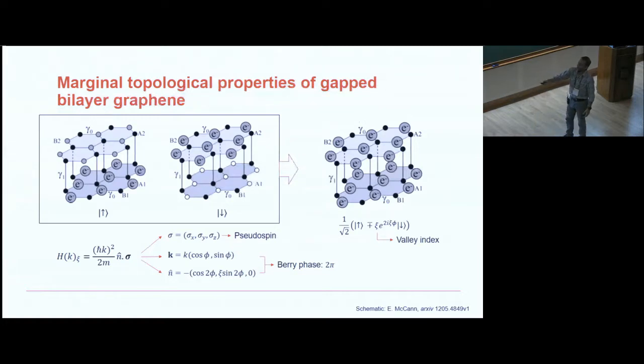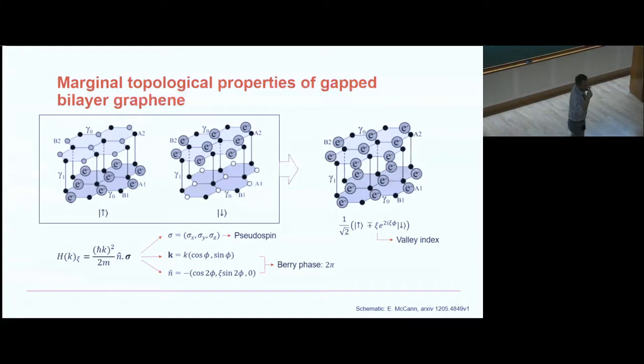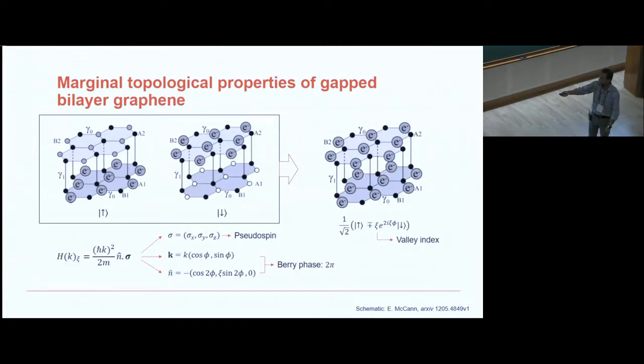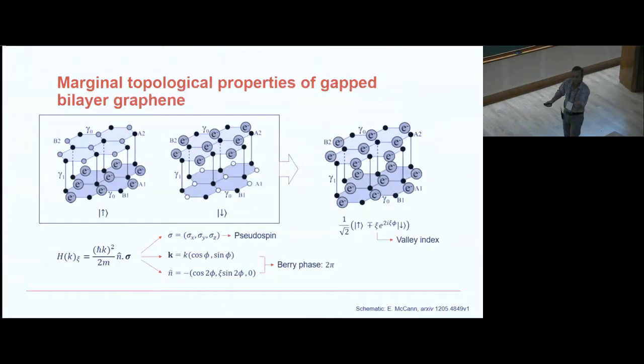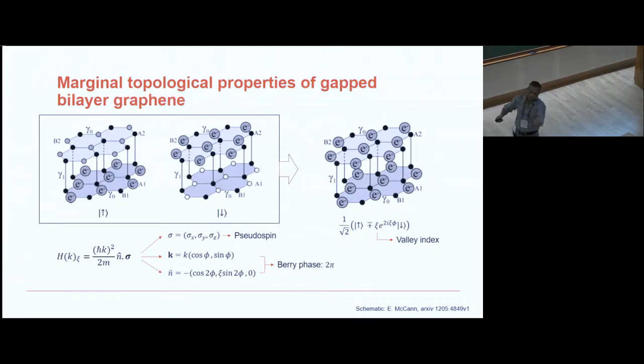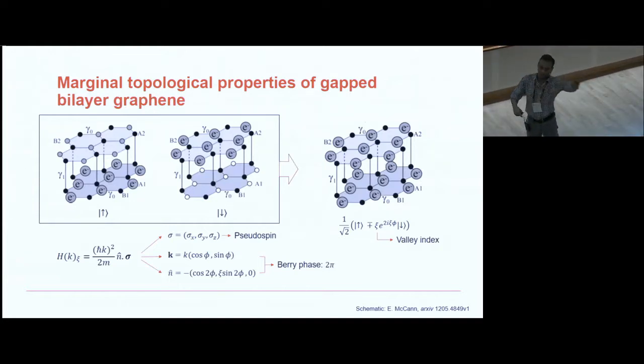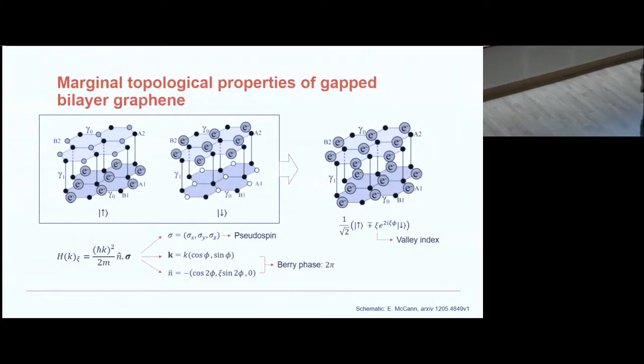And hence this is a very similar, very nice spinor Hamiltonian, which means that the carriers in bilayer graphene will be chiral. But there's a little bit of difference from the standard single layer graphene system, where sigma is a pseudospin, k is the electron momentum, but the vector here, g_k, this vector will rotate twice as fast as the momentum k. Okay, you take k in the plane, and you rotate it by phi, but this vector n will rotate by 2 phi. That means if I now go all over the k space, then the Berry phase that you will accumulate is 2 pi rather than pi in single layer graphene.